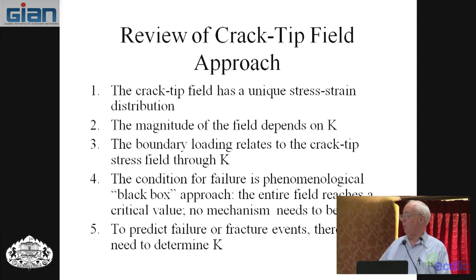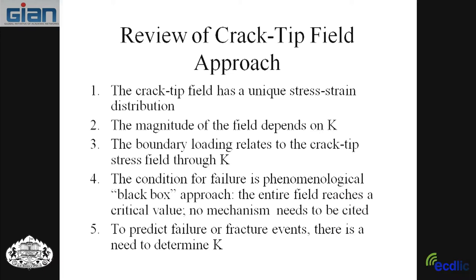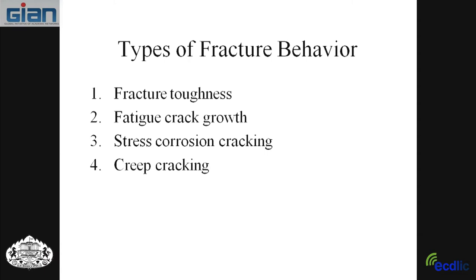So here's in some words about what I just said. We use the crack tip field approach, and the magnitude of that depends on K, and the boundary loading relates to crack tip stress field through K. So we call this phenomenological, meaning that it's the field reaching a critical value rather than a mechanism. So you don't say you get failure when stress hits a certain value, strain hits a certain value, but rather when K hits a certain value. So in order to predict failure, K is a real important term to use.